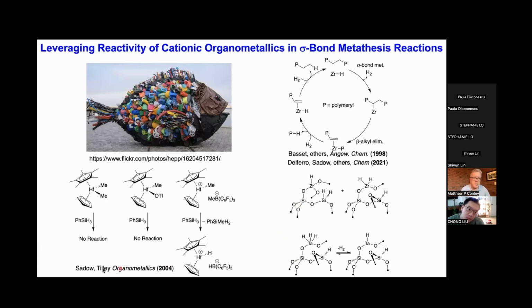And so we were inspired by work from Aaron Sadow's PhD thesis with Don Tilley. This is one of the really excellent examples, I think, that shows the effects of charge on a sigma bond metathesis reaction. A neutral Cp* Cp hafnium dimethyl reacting with phenylsilane, nothing happens. You make the triflate, which is your first generation weakly coordinating anion. There's no reaction, and that's because the triflate is bound to the hafnium center, and this is a neutral hafnium species. If you ionize it with the stronger Lewis acid, you form this weakly coordinating contact ion pair, and then this reaction becomes instantaneous, or within 5 minutes, the reaction is complete.